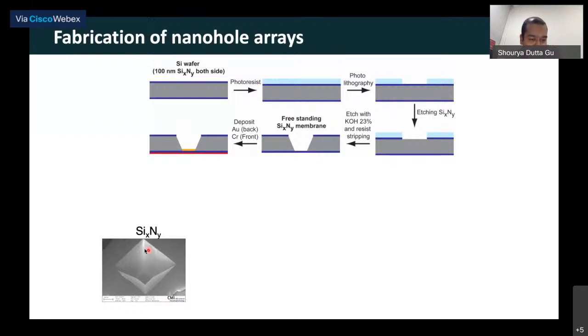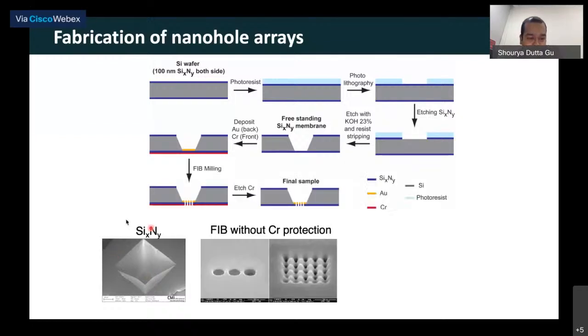So this is the pyramid shape, and this at the bottom is the thin membrane of silicon nitride that we have. Now, once we have this, we deposit a layer of gold and then we do focused ion beam milling. Now, if you have done FIB or you have studied FIB, you know that if you have soft materials like gold, you will mill them off at a very fast rate. So before you can actually make through holes, you will have the gold getting removed. So this is a typical example of when you do milling without any protection, any hard layer on top or a hard mask at top.